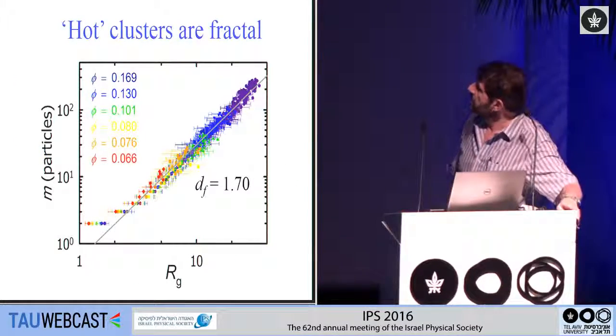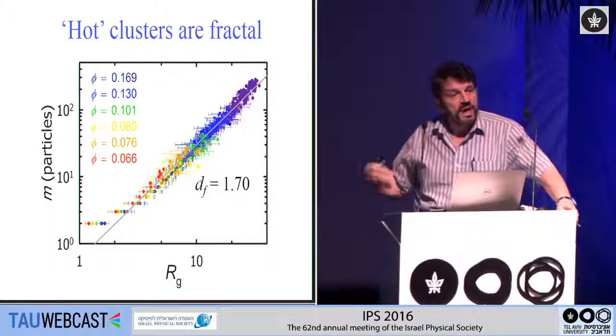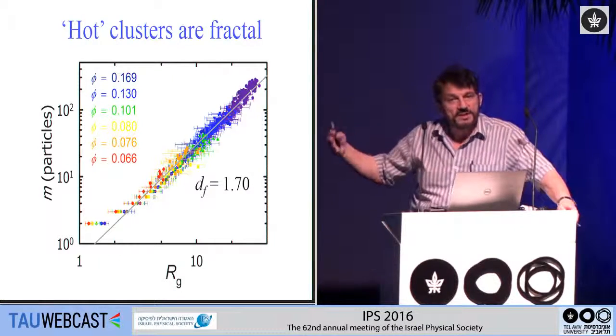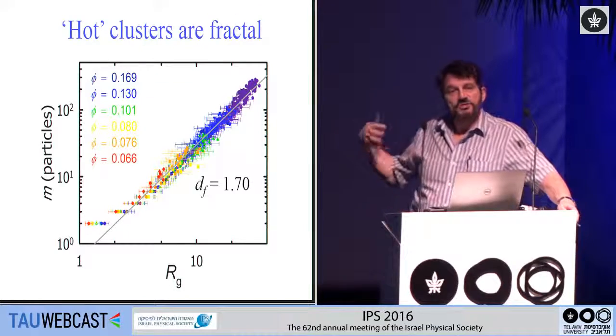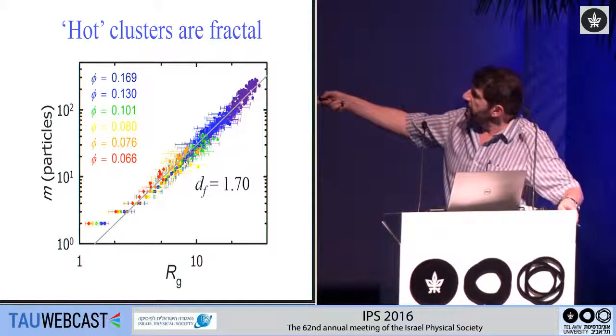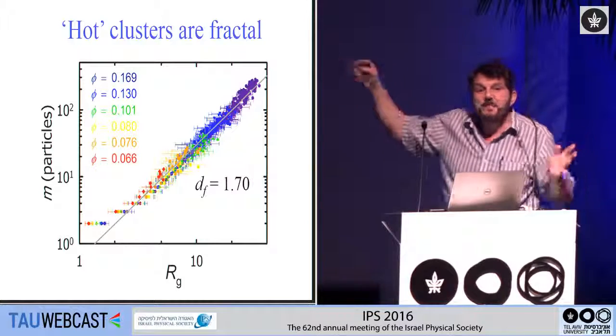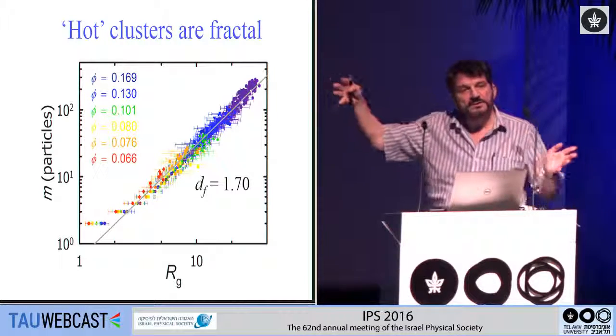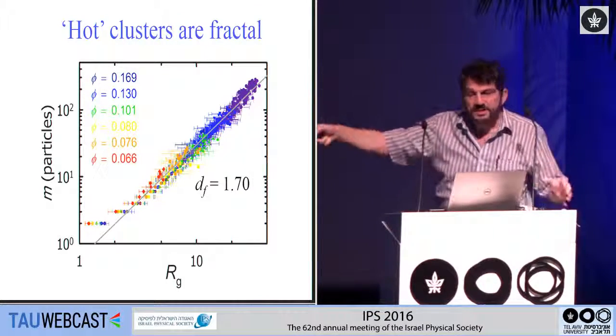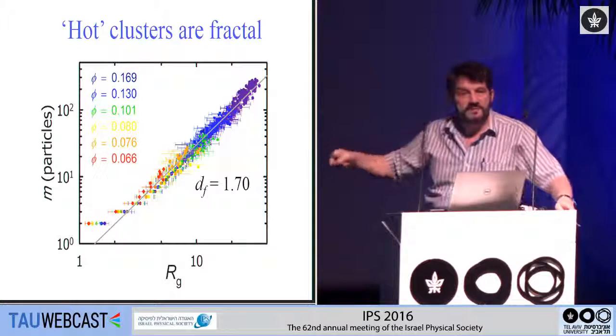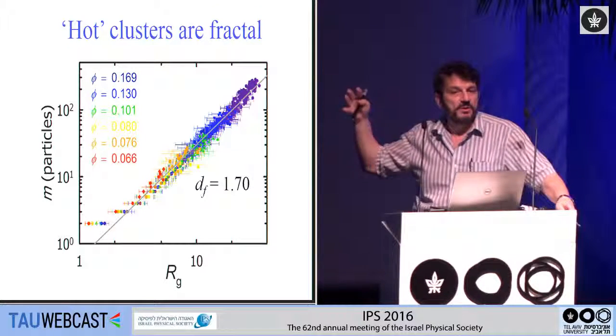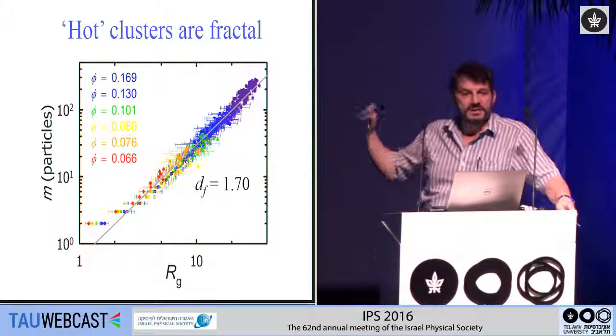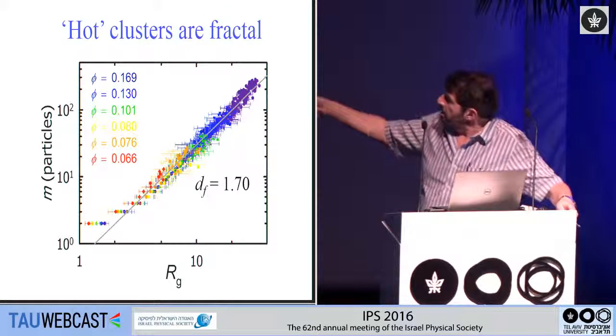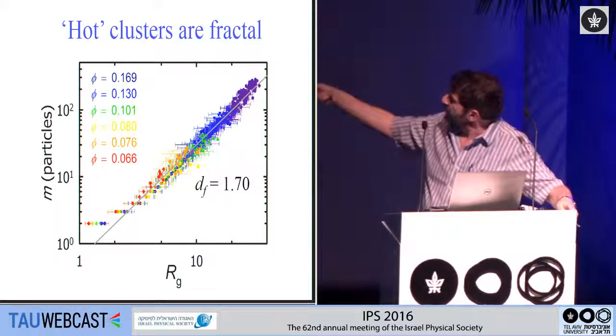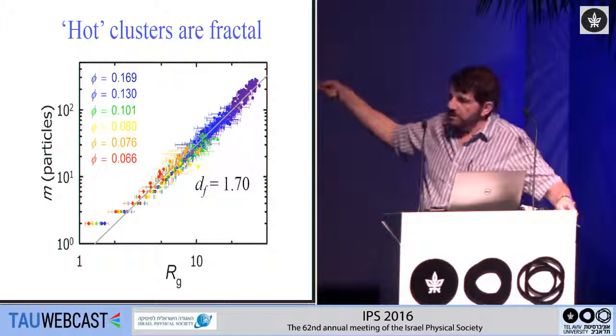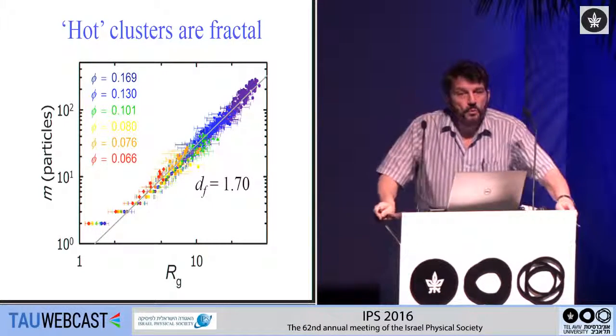The first thing that we can do is measure the structure of these correlated regions. And not surprisingly, this structure is fractal. So if you plot the number of particles, that's the mass of these clusters, the number of particles in each of these clusters as a function of the radius of gyration, just calculating the radius of gyration as you would normally calculate it for a polymer, you see that there's a very strong correlation, and it's a power law correlation. The fractal dimension is about 1.7.